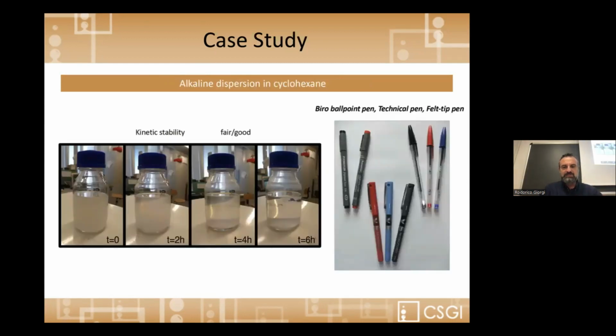Just the last slide, just to say that these particles can also be dispersed in low polar solvents, for example, cyclohexane. This is pretty relevant when we talk about graphic materials, contemporary graphic materials, like, for example, biro, ballpoint pen, technical pen, felt tip pen. In this case, we have formulations that are fairly stable, kinetically stable. You can see here the sedimentation rate of these systems, but nanoparticles can be dispersed for an acceptable time range for the application, for example, using the spraying technique.